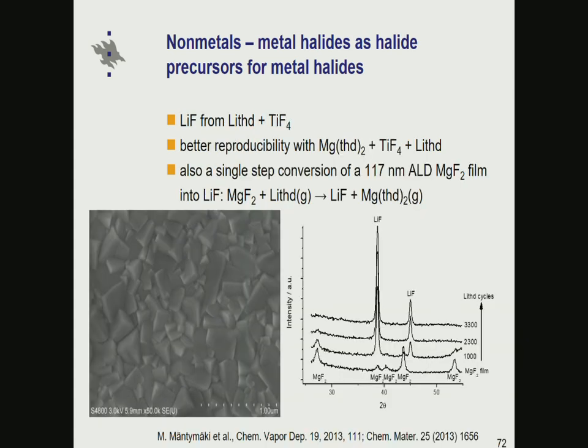And we have used the same also for lithium fluoride, so lithium THD plus titanium tetrafluoride. And quite an interesting thing here was, there was a little bit of talk about conversion reaction. So here we exploited a conversion reaction as well. These direct lithium fluoride processes are a little bit tricky to control. So therefore we had a look also at the possibility that we first use a very robust process which is depositing magnesium fluoride, and then just expose this magnesium fluoride to lithium THD.